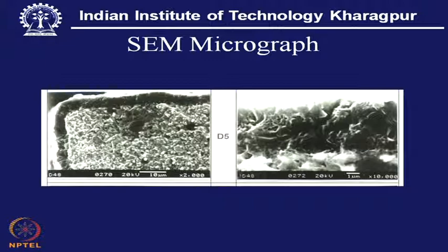So, this is tungsten carbide and cobalt. The toughness of this substrate is extremely important, and for that, when we see that fractograph, we can see the average grain size which appears after fracturing. This SEM picture covers the entire information on this coating up to this surface, and there we can see to what extent this coating is an integral part of this substrate.